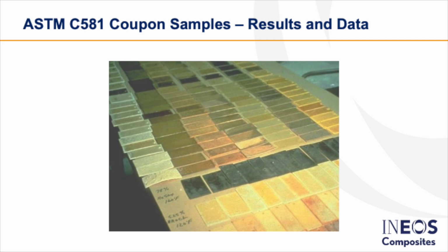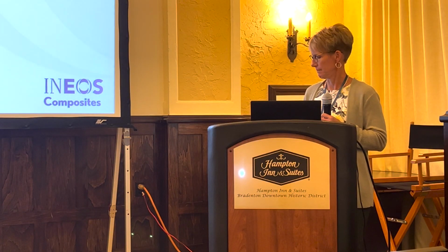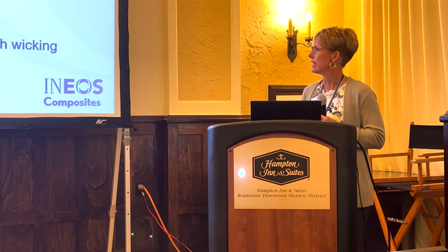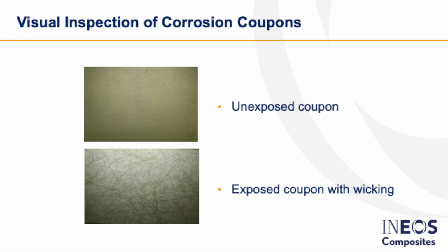This is just a picture of many coupons that have been exposed to different environments. Just gives you an idea of the different types of attack we see. Sometimes the coupon has a very minimal change, whereas some of these, depending on the environment, really change a lot. Again, an example of an unexposed coupon, and then one that we would evaluate where we would see some wicking. You use a backlight to be able to see how that coupon has been attacked in that environment.